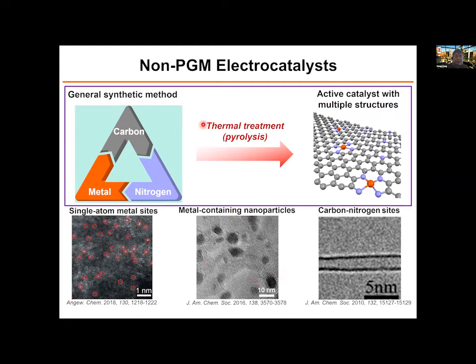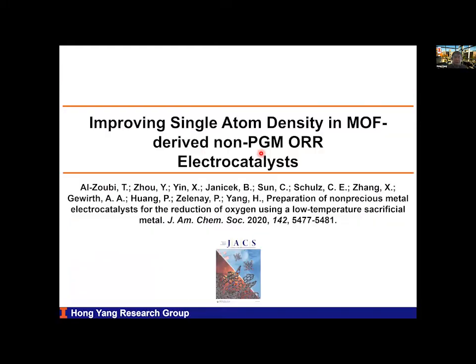So for the non-PGM catalyst, this is primarily based on the metal, nitrogen, and carbon, a three-element-based system by and large. The common consensus is that the single atom metal sites around the nitrogen and carbon matrix give the highest activities. So this leads to a general strategy to improve the performance by reducing the metal particle formation through the pyrolysis processes using well-defined structures. One of the common strategies is to use a sacrificial metal-based so-called ZIF-8 metal organic framework. And so in this recent study, we try to increase the single atom densities by lowering the temperature using alternative sacrificial metals.